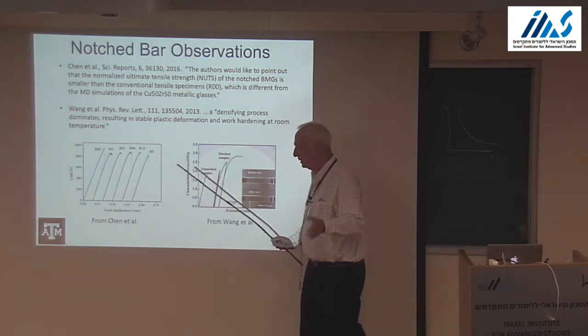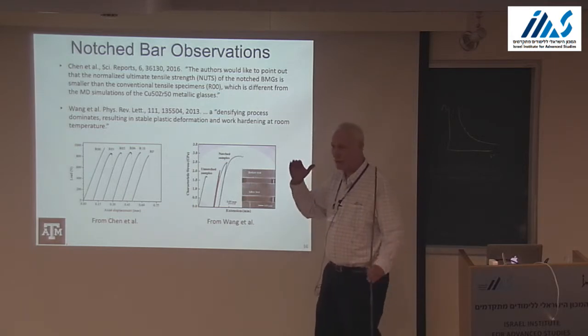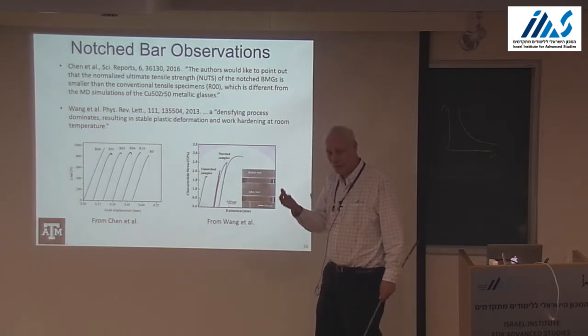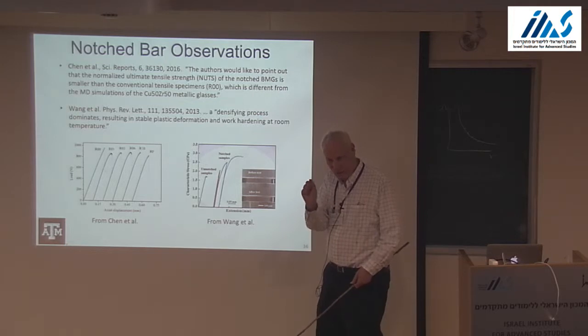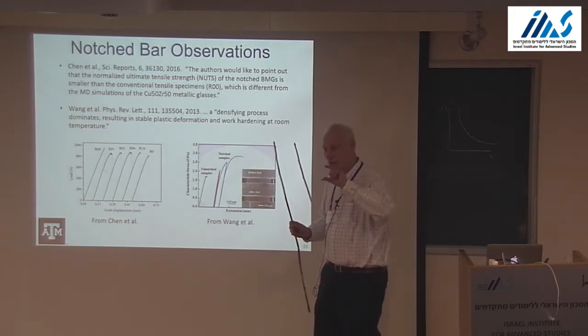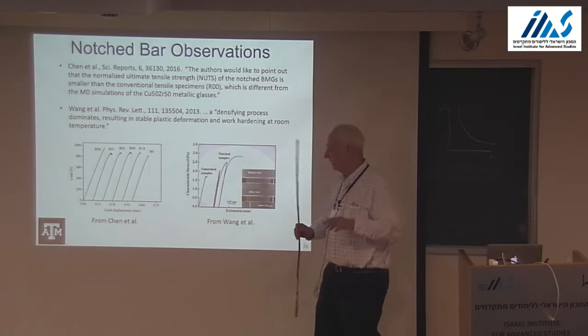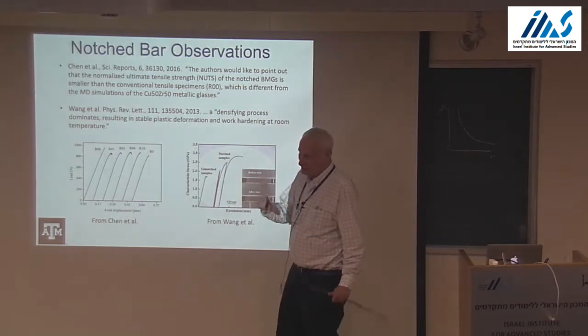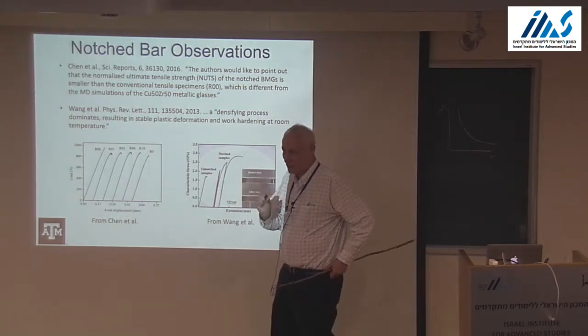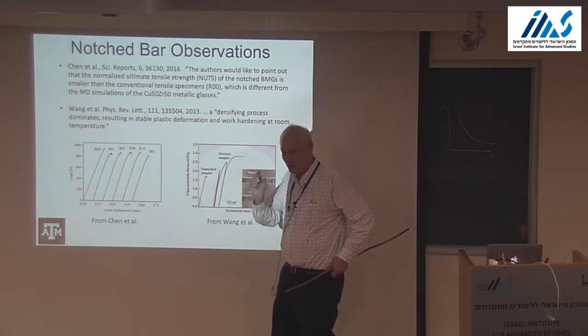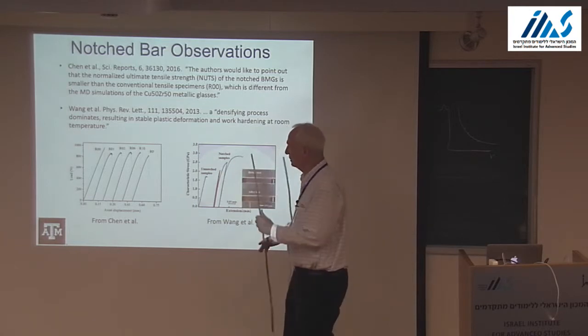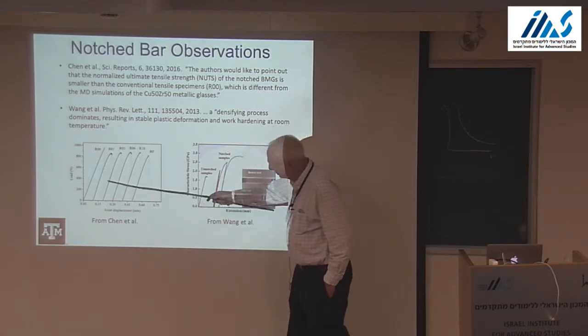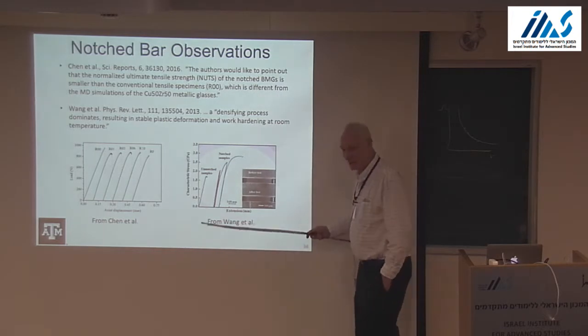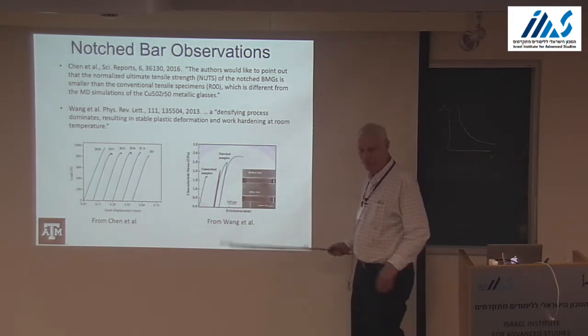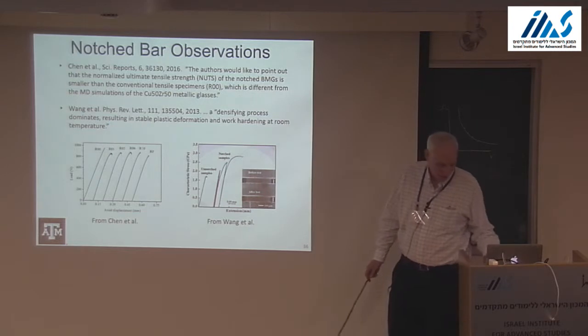So here are some observations. For ductile materials, one gets something called notch strengthening. You take the force divided by the width between the notches, looking at notch bars, and it's greater for a notched bar than for an unnotched bar. For brittle materials, you usually get notch weakening. The force divided by that width is less than for a bar without notches. Here, experiments that show notch weakening. Here, experiments that show notch strengthening. So you see both of these experimentally.